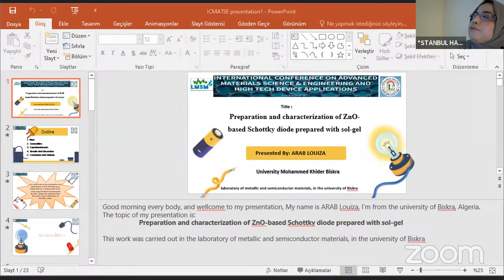Key results include that all films exhibit a polycrystalline hexagonal wurtzite structure. The energy band gap values for the films deposited on ITO substrate are 3.25 electron volts for undoped, 3.27 electron volts for ZnO doped with gallium, and 3.1 electron volts for ZnO co-doped with aluminum and indium. The films and diodes show high transparency, over 90% in the visible region. The electrical resistivity values for doped and co-doped zinc oxide films decreased compared to undoped zinc oxide, as shown by these values. The diode displays Schottky-type behavior.